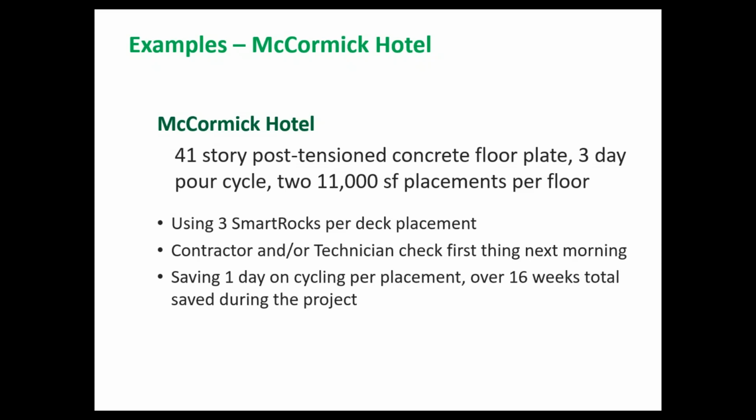McCormick Hotel, again in Chicago, is a 41-story post-tension concrete floor, and they had two 11,000 square foot placements per floor, and they used 3 SmartRocks per deck placement, and they were checking the sensors first thing in the morning, and that helped them.